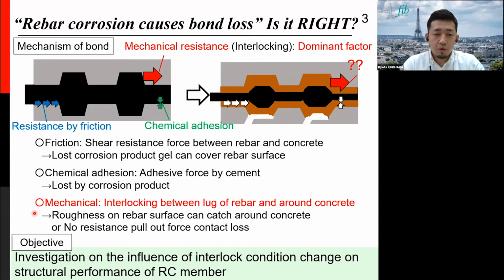And the mechanical bond is led by interlock between lugs and concrete. The rebar corrosion changes the rebar surface shape, but the interlock has the possibility to be kept. In general, it is said that rebar corrosion causes bond loss. However, that is just under the overall image, including these three phenomena. So considerations focusing on each component of bond were few. So this study focused on the dominant factor, the interlock effect, aiming at an investigation of the influence of interlock condition change on the structural performance of RC members from experimental and analytical approaches.